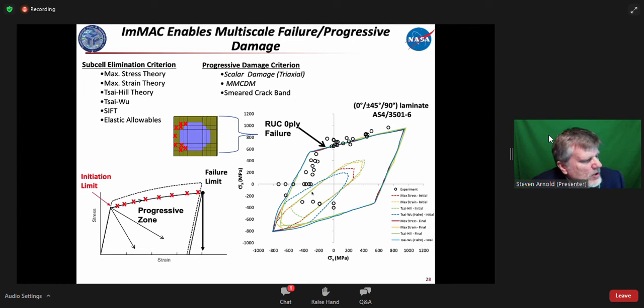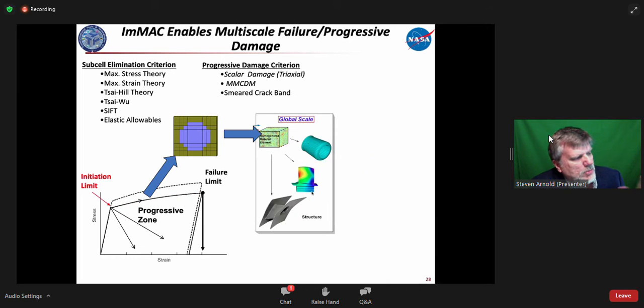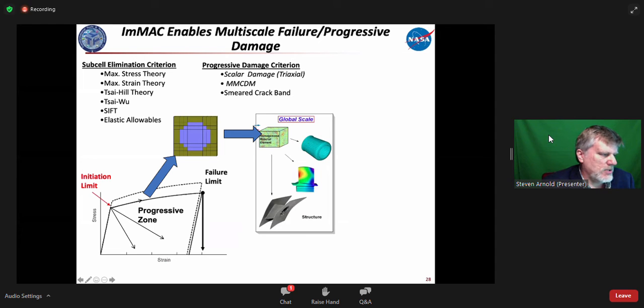And then obviously, once we've done this now for an RUC, we can now actually take that RUC, plug it in at an integration point within the global finite element solution, and again have progressive damage take place now at the global scale, where the finite element is redistributing stresses throughout the structure based upon failure at the various integration element locations. And then the micromechanics is dealing with redistribution of stresses within the RUC due to damage at the various locations within the structure. And this is done iteratively until obviously you can predict component failure.